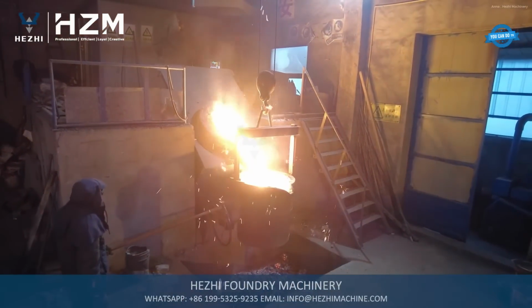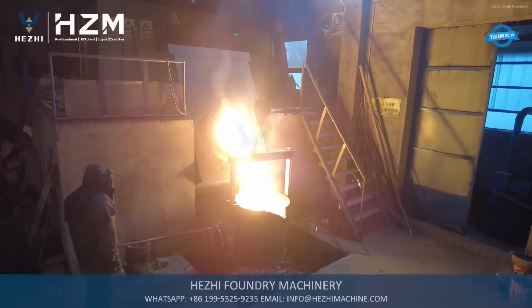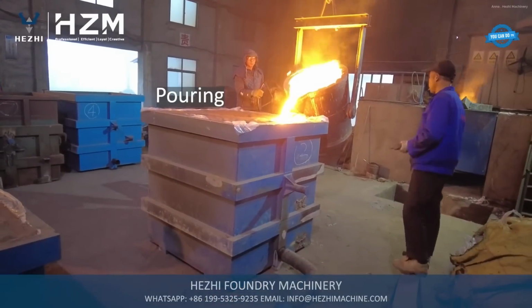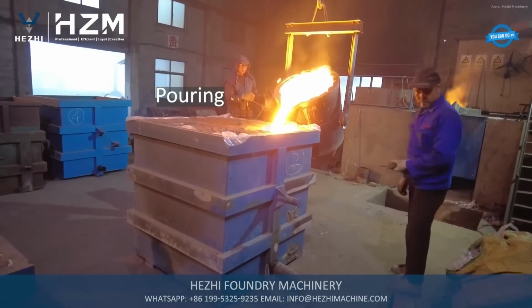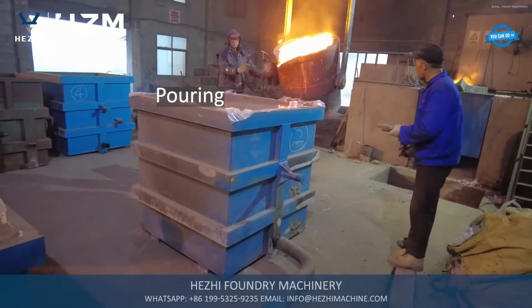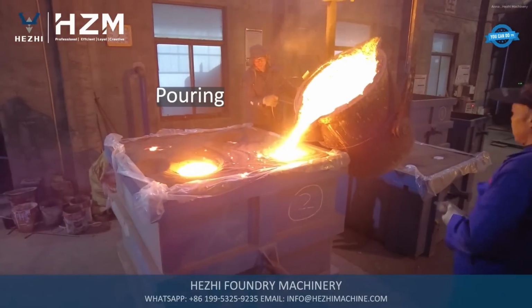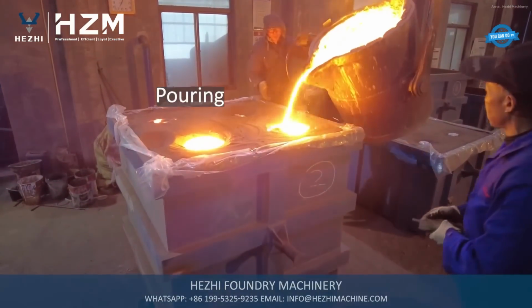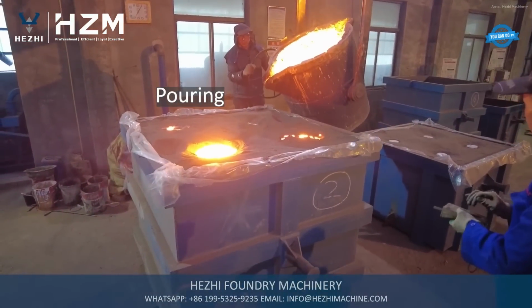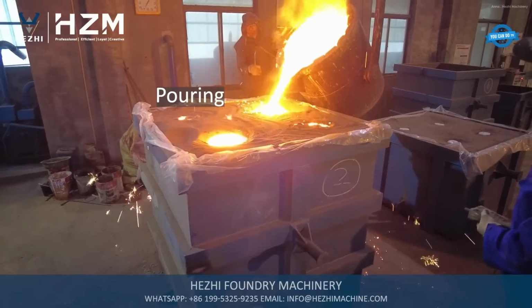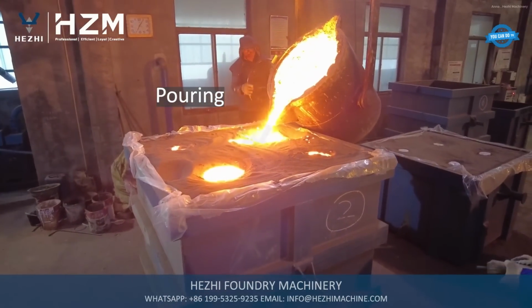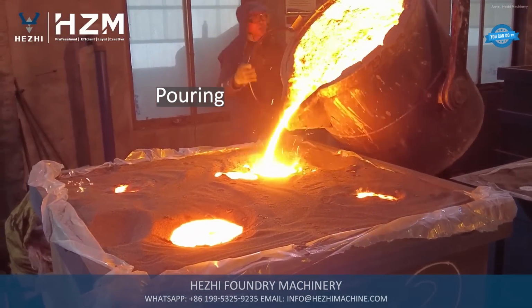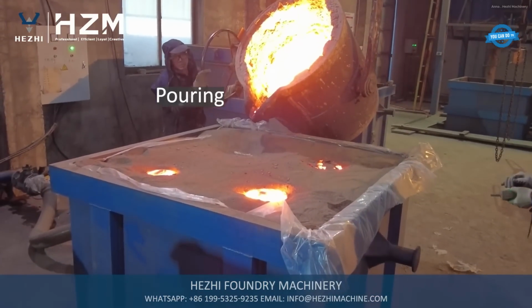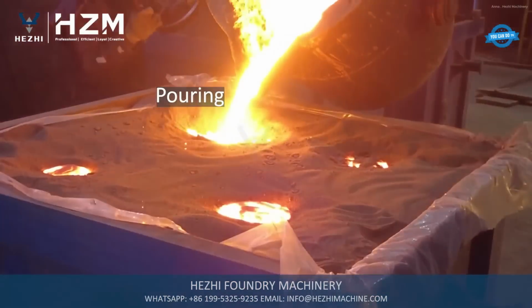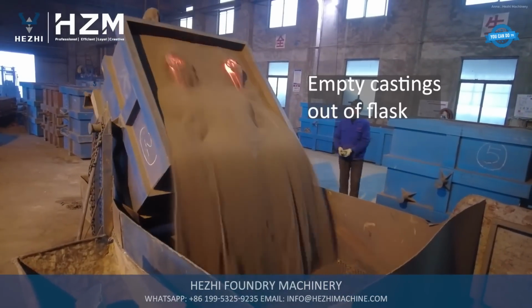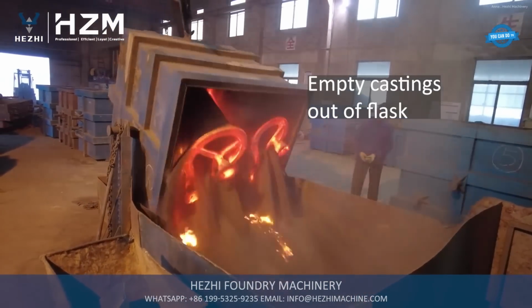Patterns are carefully positioned inside a molding flask and surrounded by sand. The sand is compacted using a vibration table to eliminate voids and support the foam structure. Pouring basins, runners, and risers are glued onto the setup. Molten metal is smelted and then poured directly into the flask, replacing the foam with steel as it vaporizes. Once solidified, the flask is emptied and the castings are transferred to storage. Final processing includes shot blasting to remove residues, revealing clean, high-precision castings ready for further machining or assembly.